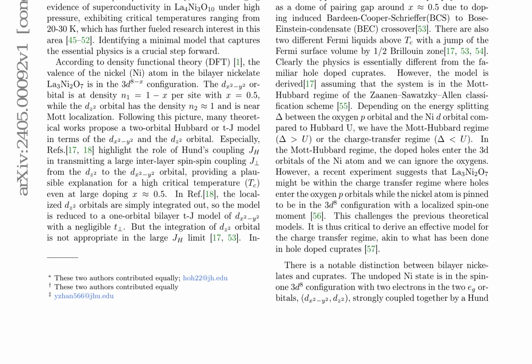The lattice structure and p, d orbitals of the bilayer nickelate La3Ni2O7 are illustrated in Figure 1. The symmetry analysis of the orbitals is provided in the supplemental material. In bilayer nickelates, a theoretical model is presented for the Zhang-Rice singlet state, a phenomenon observed in the charge transfer regime. This model is based on a multi-orbital Hubbard model, incorporating the d orbitals of Ni atoms and p orbitals of oxygen atoms. The Kondo couplings, JK,A and JK,Z, describe the interactions between these orbitals.